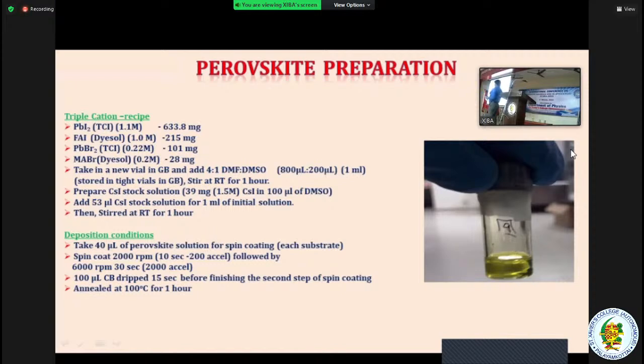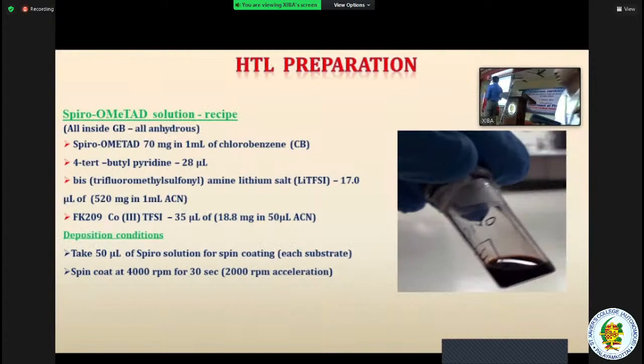For the perovskite layer preparation, that is the recipe. Different materials are used, such as lead iodide, formamidinium iodide, lead bromide, and methylammonium bromide. These are some of the materials used to make the perovskite layer. After making the solution, we used spin coating to get the proper thickness of perovskite. For spin coating we have to adopt certain conditions, otherwise we won't get a proper perovskite layer. Next slide, this is the HTL preparation, with the materials and deposition conditions. Again, we use the spin coating method for the preparation of the HTL.